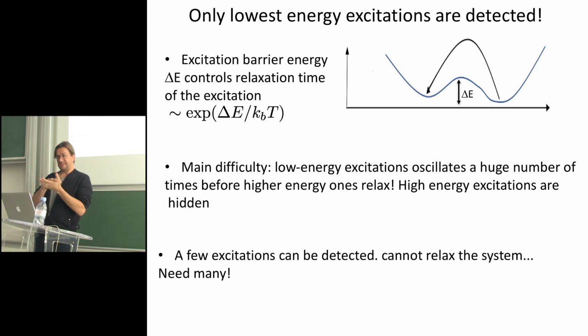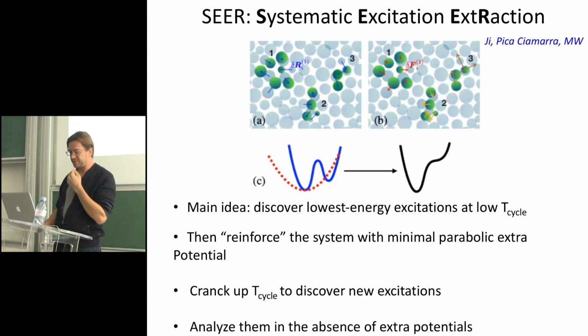So a big difficulty in extracting excitations is that if you take a numerical system and you go at very low temperature to excite them, you will see the few low energy ones. As you crank up the temperature, the low energy ones, because their time scale goes exponentially in their energy, will start flipping hundreds of times before you see more interesting higher energy excitations. So you can only get a few excitations with a method like that because the larger energy ones are hidden by the super high frequency ones that keep jumping around and screw up your analysis. They hinder your analysis. Okay, so the key idea in this first project is actually to introduce an algorithm that can deal with this problem.